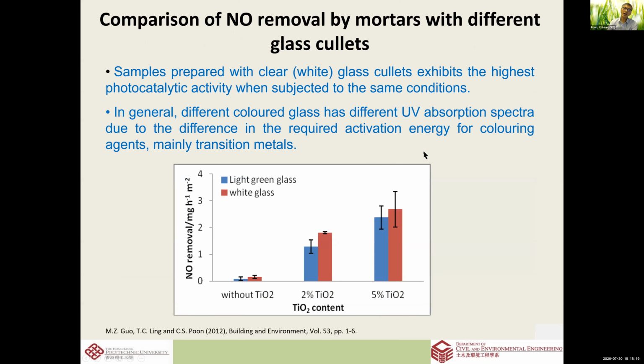So we are very happy with that, and then we tried out different types and colors of glass. As I said, the lighter the color, the better, because it allows better penetration. It will not absorb too much of the UV or the sunlight. And then this is without TiO2, the removal is minimal, no removal. With some TiO2, there's some removal, and different colors of glass on top have different removal ability. So definitely the glass does affect it. The white glass, that means the clear glass, is the best.